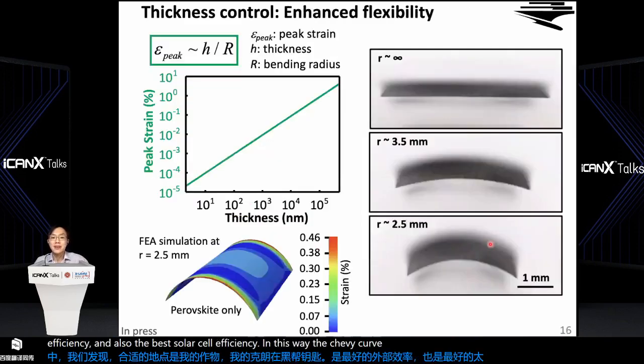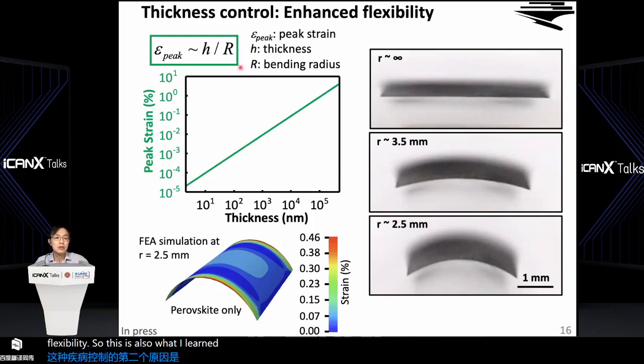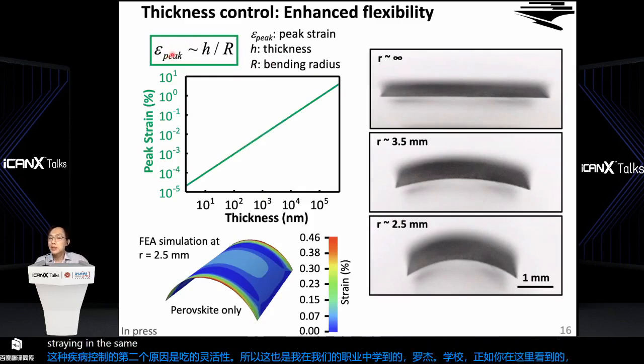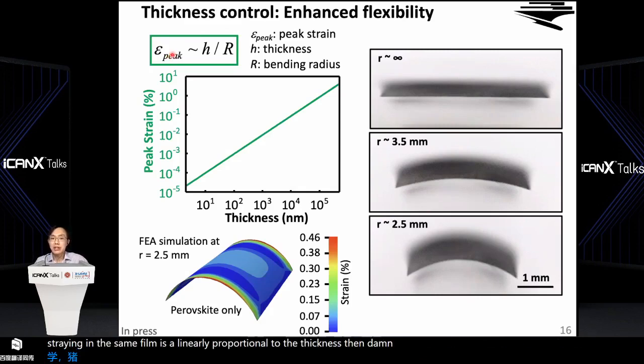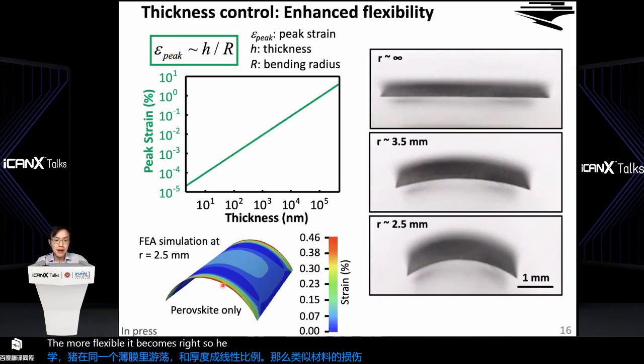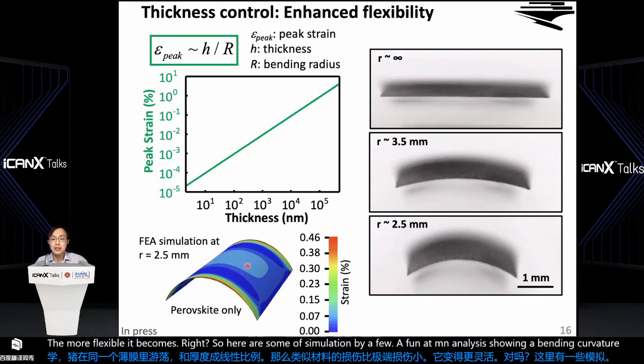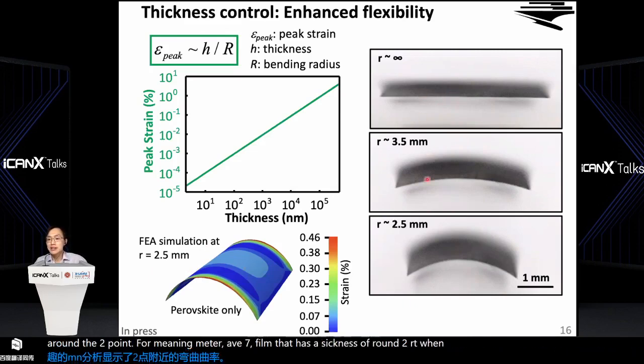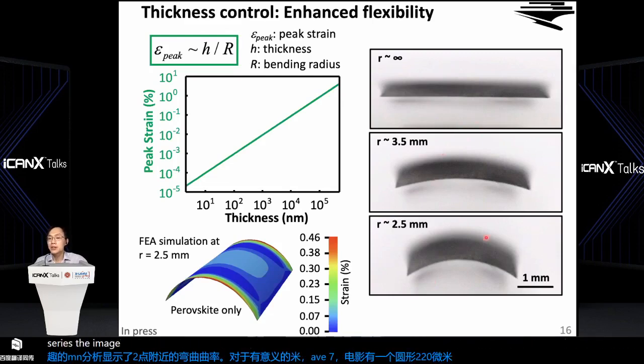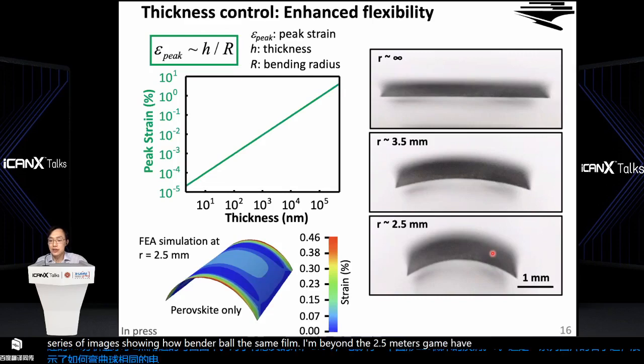The second reason for this thickness control is to enhance the flexibility. This is also what I learned in Professor John Rogers' group. As you can see here, in conventional mechanics, the peak strain in this thin film is linearly proportional to its thickness. That means the thinner the material, the smaller the peak strain, and the more flexible it becomes, right? So here are some simulations by finite element analysis showing a bending curvature of around 2.5 millimeter of a thin film that has a thickness of around 20 micrometers. Here on the right-hand side are a series of images showing how bendable this thin film is, right? Beyond 2.5 millimeter, you have this fracture showing up.